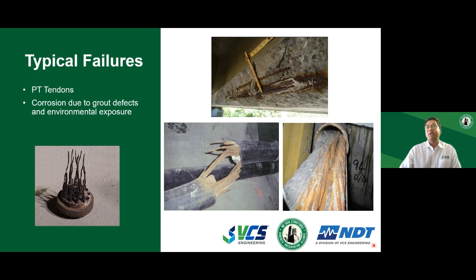Here are some pictures which highlight typical failures. The one on top is a bridge in Pennsylvania. Here you can see the regular conventional steel reinforcement. You also see a post-tensioning duct here, which is completely corroded, and now you have the strands exposed to chloride contaminated runoffs from the deck. So essentially, the rebar corroded first. It led to cracking and effectively spalling of the concrete, which led to a direct path of chlorides to the metal duct, which resulted in severe corrosion and heavy section loss of the duct. Effectively, that resulted in the exposure of the tendons.